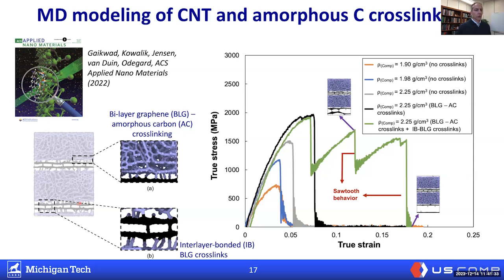So on the left here, what you see is a diagram of the molecular dynamics model. Not only are we looking at creating crosslinks between the carbon nanotubes and the amorphous carbon, in this model there are actually two parallel aromatic planes right here. That's to model the flattened carbon nanotube. All right, our MD models can't be really big, so we can only do a little section of it here. But we played around with putting crosslinks between the amorphous carbon and the carbon nanotubes.